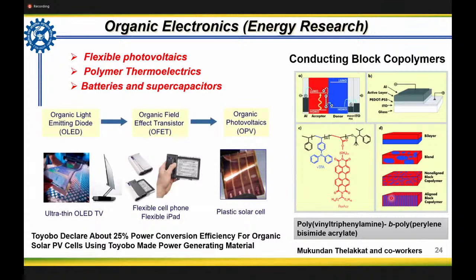Unfortunately, controlling the morphology is one of the challenging issues, particularly with conducting systems having donor and acceptor units. It's very difficult to organize them like this because their chain folding behavior is not as simple as other semi-crystalline systems, because a lot of complexity is involved. Then there will be a competition between crystallization and microphase separation that leads to disordered morphologies, as shown here in this cartoon.